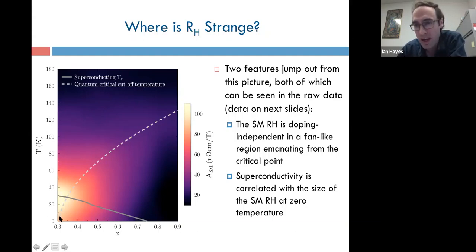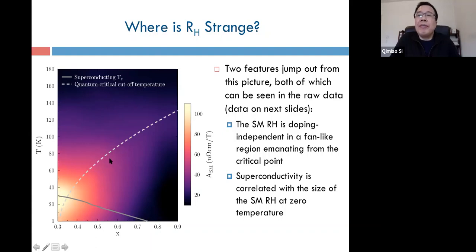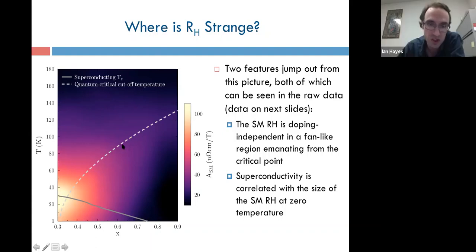The other thing I'll point out is that the antiferromagnetic phase actually ends at 28%. So I'm a bit off the exact critical points, you might say. And that was chosen to just make sure we avoid accidentally entering the antiferromagnetic phase. Fair enough. Your observation is fair, and this is really just a guide to the eye determined by the data points that I have. And there's only so much I can say down here. But it may well be consistent with a small cutoff.